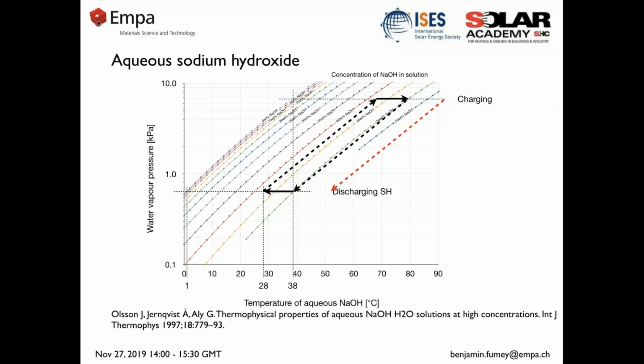And the gross temperature lift that I'm able to reach in the discharging, and of course very important in the discharging also the minimum concentration that I will get, which then leads to my maximum energy density that I can reach. Here, just to point out, you see in the red dashed line is the fact that in our case with sodium hydroxide, we do not want to go beyond 58% because we have a liquid sorption system, and sodium hydroxide tends to crystallize above 58% in room temperature. So we already see here now with these defined temperatures, we have a slight limitation in our case with sodium hydroxide